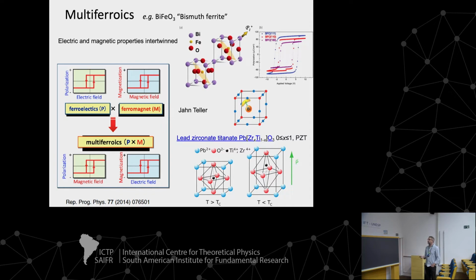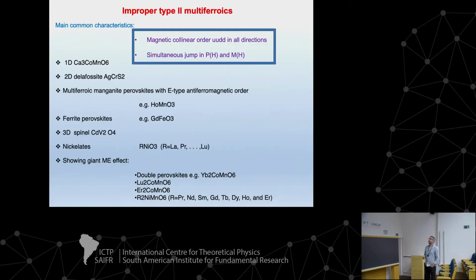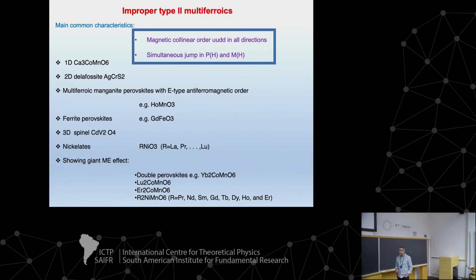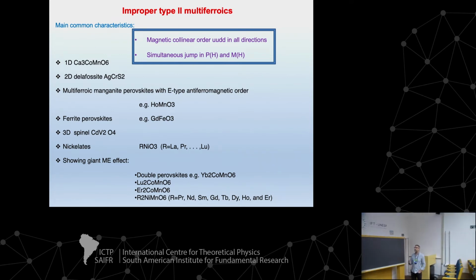In general, what happens is that there is some Jahn-Teller type distortion at low temperatures that generates some polarization. Then you want to see whether a magnetic field can modify this structure to get a modification of P. This is the particular type of multiferroics I will discuss today, which are called type 2, because in these type 2 multiferroics both transitions occur at the same point. That means a ferromagnetic or antiferromagnetic and a ferroelectric transition.